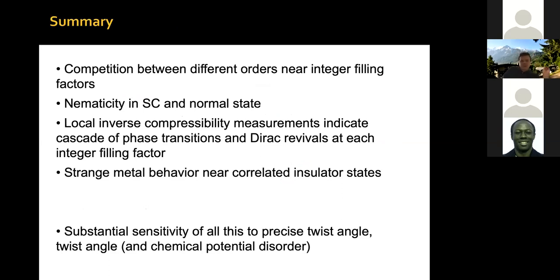I have told you today that there seems to be competition between different orders near integer filling factors in Magic Angle Graphene. Okay. In particular, there is a region of normal state nematicity or anisotropy in the resistance, which leads to depletion of Tc. And everywhere in the superconducting dome, there is a nematic response of the superconductivity. Our local inverse compressibility measurements indicate a cascade of phase transitions and Dirac revivals at each integer filling factor. And we can see that there is a strange metal behavior near the correlated insulator states in Magic Angle Graphene.